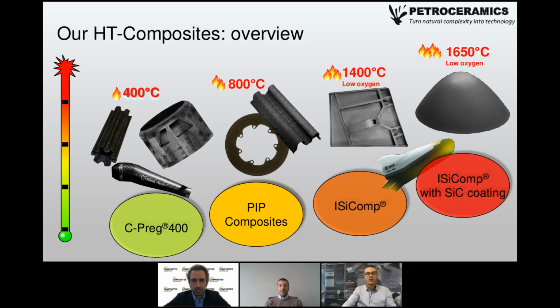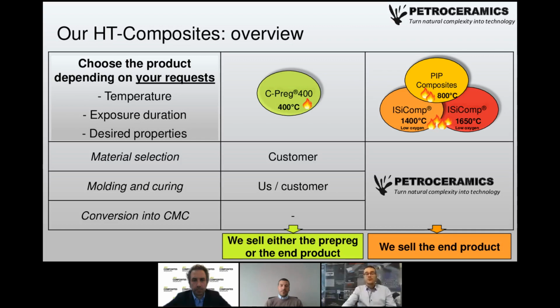But if this is not enough, we have a line of carboceramic composites, so carbon matrix composites, which can withstand prolonged exposures up to 1400 Celsius degrees in inert or low oxygen atmospheres. And these materials find application in the aerospace sectors, among the others, for which they were originally developed. We also developed a specific protective coating that allows these materials to withstand even higher temperatures, as you can see. So we can provide different solutions for different temperatures, for different exposure durations, and based also on the desired properties. So basically, based on your needs, we can propose different materials.